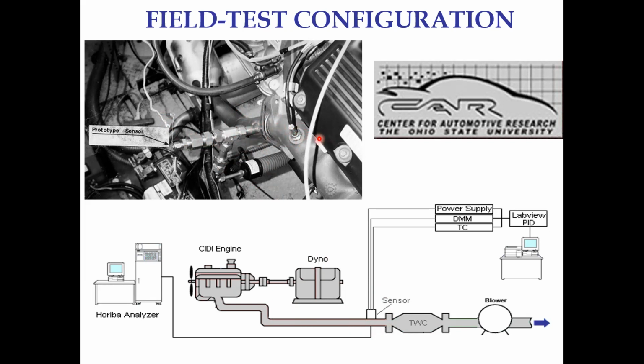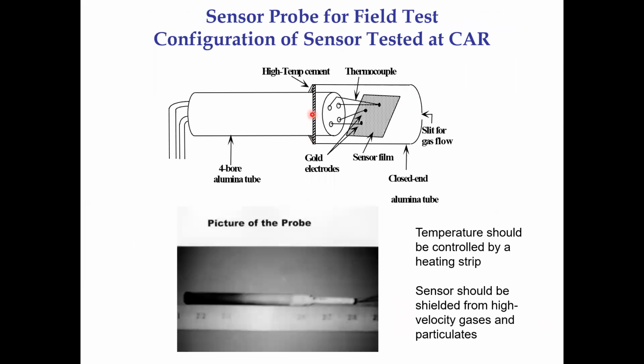So this is what we do. And to show you some of our probes, here's a screen printed sensor with two probes for measuring the resistance change. And there is a thermocouple to monitor the temperature, so this sensor doesn't have a back printed electrode for electrical heating. So we have to monitor the actual temperature of the sensor using a thermocouple.